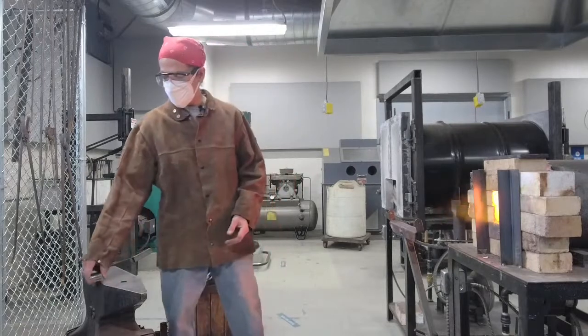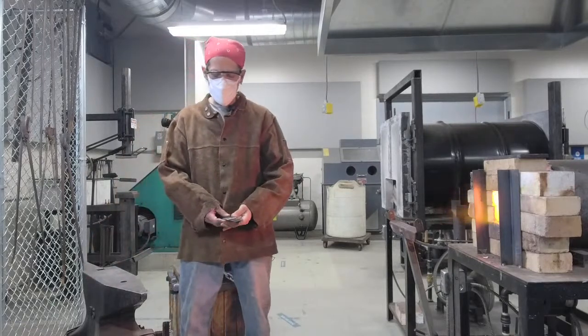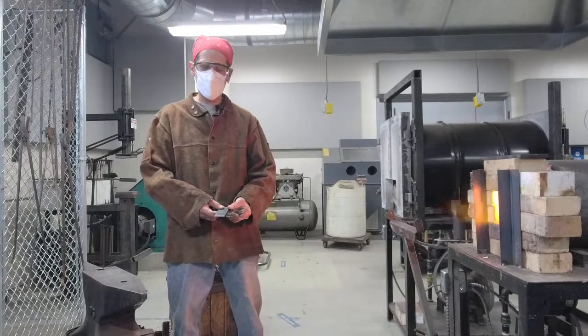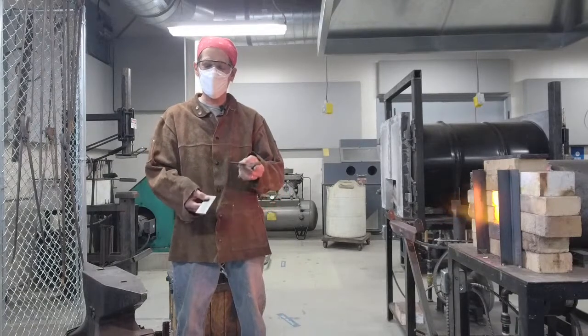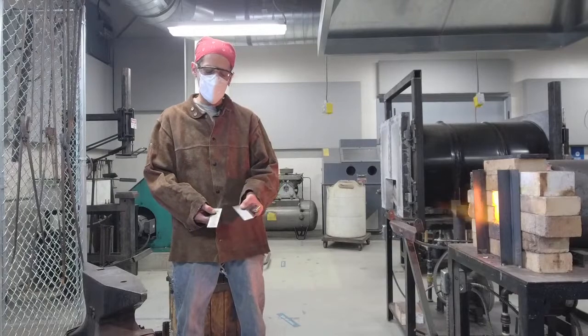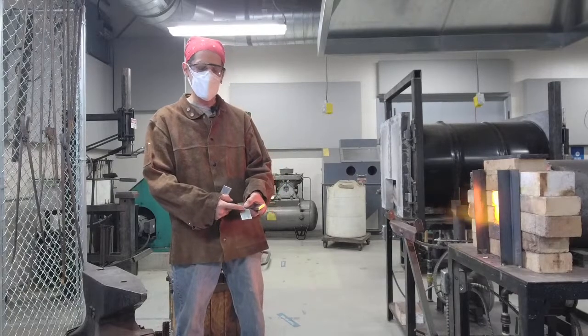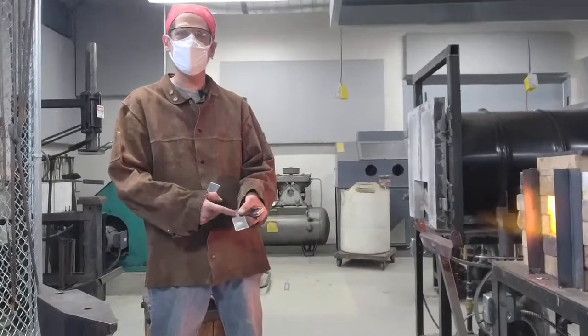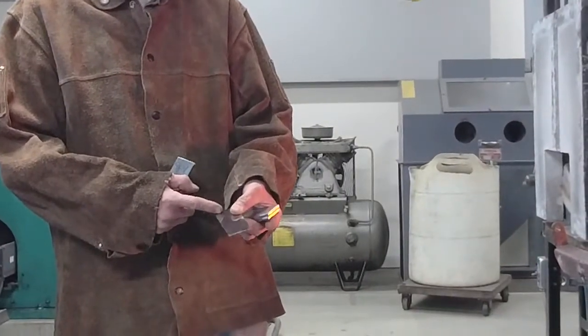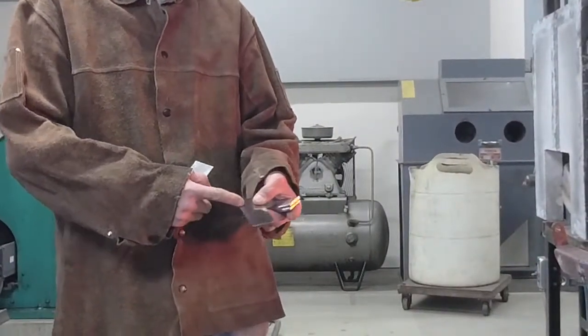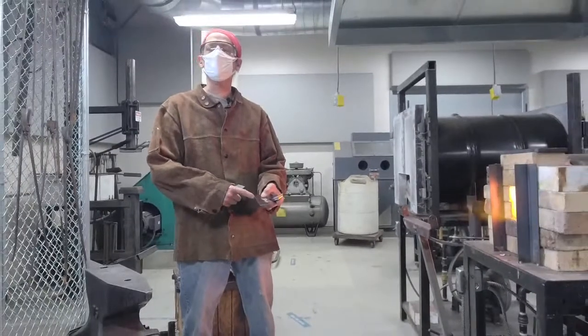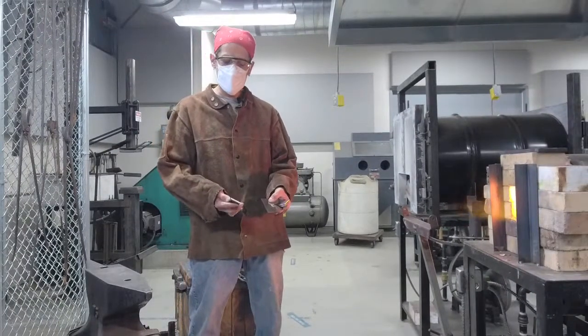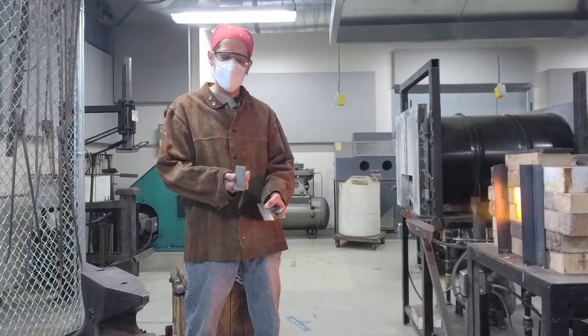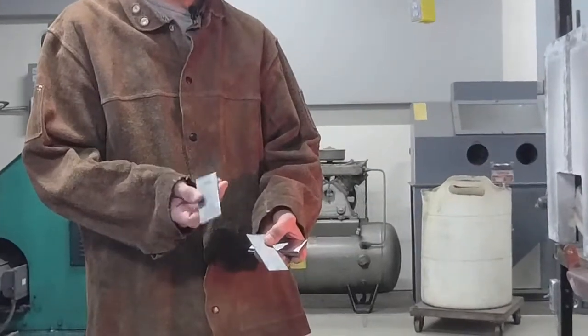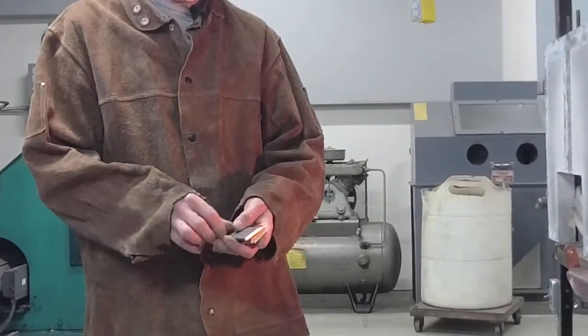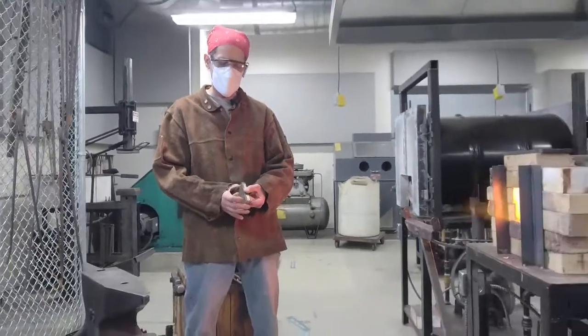What I'm starting with is two alloys of steel. So to create contrast, I use two different types of steel. One is called 15N20. It's the same type of steel used to make bandsaw blades, or most bandsaw blades. So it has a high nickel content. So this will give me a shiny layer in the steel. The other steel I use is a straight high carbon steel called 1080. This is a very forgiving and easy to weld combination.